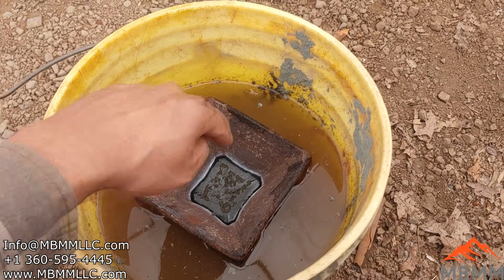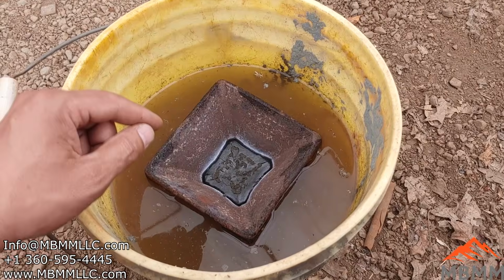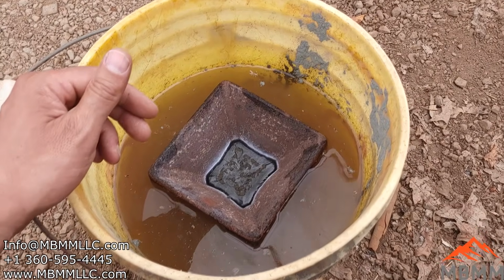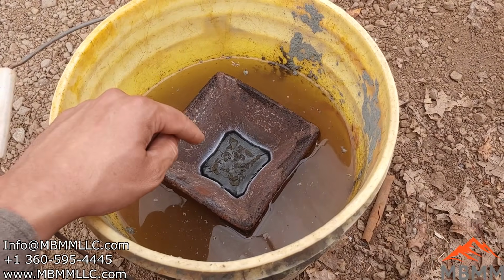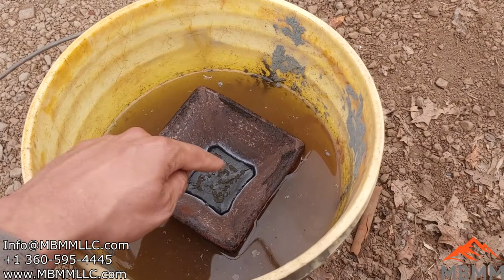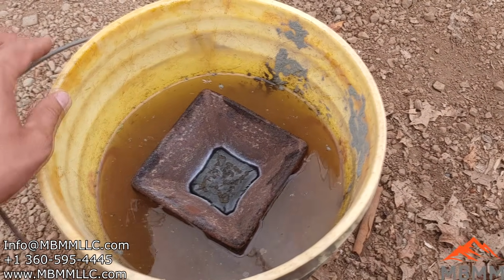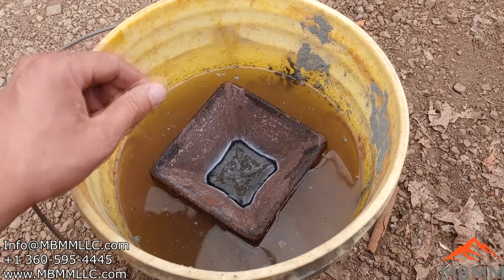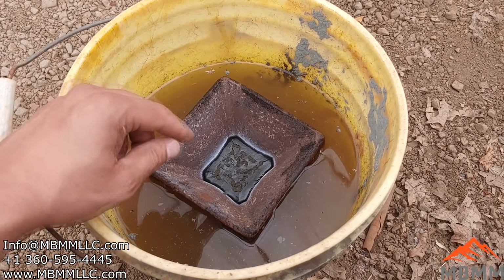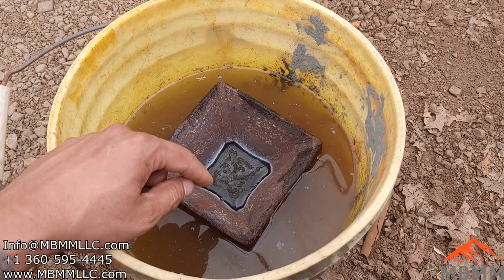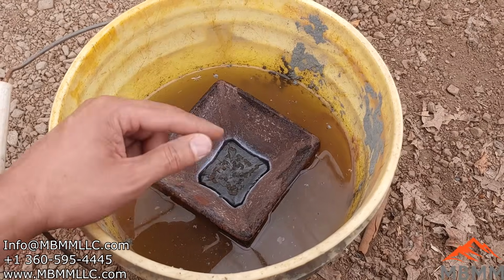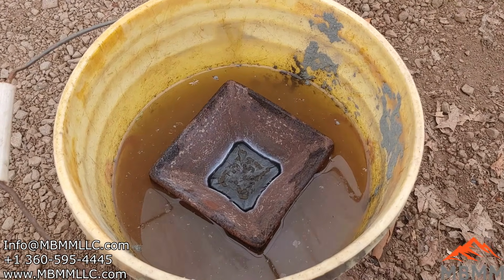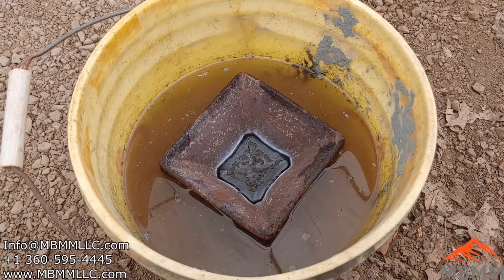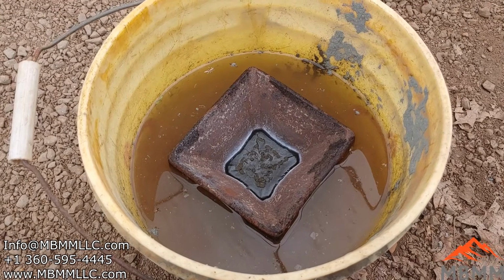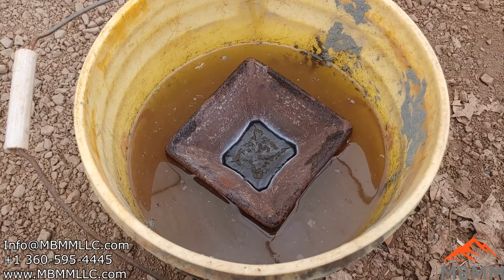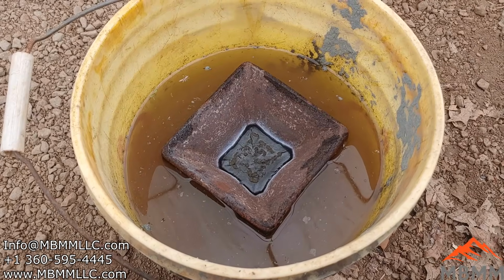So that's why right now, especially with lead, I use water just to make sure the very tip of that cone down at the bottom cools off, below, I don't know, whatever it is, 600 degrees Fahrenheit. And it doesn't take too long in the water because the bottom of the cone has such high surface area for the volume. So I just dip it in here for a minute or so once it's solidified all the way on the top. And then now we'll get it tipped out and see how much metal we have in the bottom of our cone mold. I started with 50 grams, so we'll get this weighed and see how much lead we have from 50 grams of material.